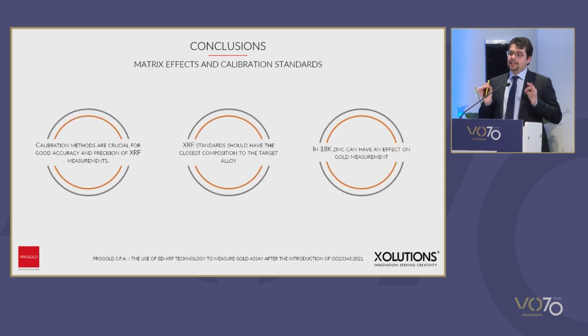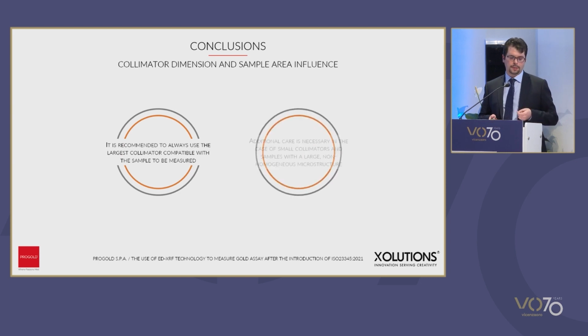So, in conclusion, what is the result of our work? Well, calibration methods are fundamental in order to guarantee the accuracy of the measurement by means of X-ray. And as you could see in the previous slide, it is indispensable that the method used for the analysis has been calibrated based on an alloy which is as close as possible to the object that we want to test, because if the deviations are very small, well, they can have an impact on the fineness, on the evaluation of the object. We've seen that zinc can have an impact on the performance of the measurement, and so we need to consider the effects of these elements on the performance of the instrument.